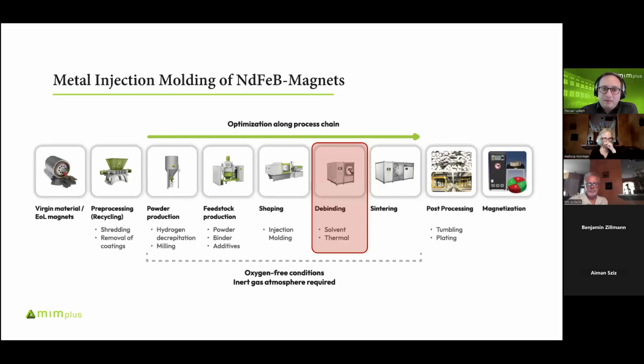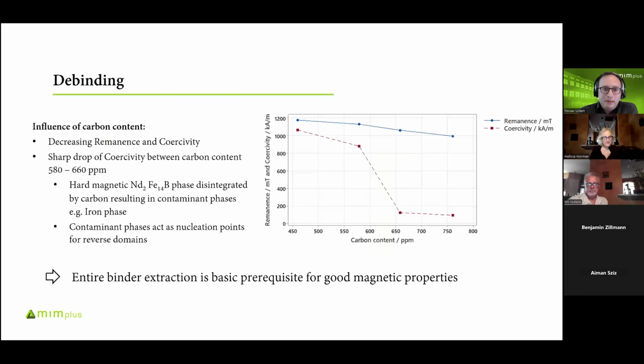Then after the shaping, we have the debinding step. And it's really crucial to remove nearly 100% of our binder. That's also a lot of development work we had to do in the past. These are some experiments I did a few years ago. We have here on the y-axis the remanence in blue and the coercivity in red as a function of the carbon content in our magnet.